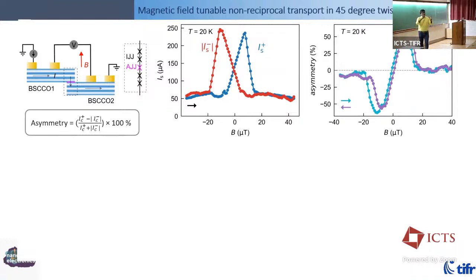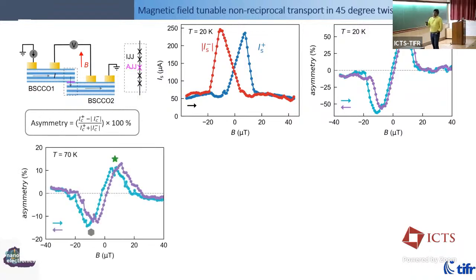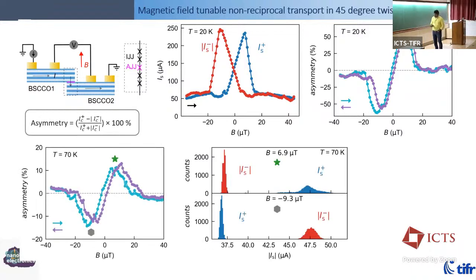So we had to build a special setup, a cryoperm box, to shield out Earth's magnetic field, and then have an electromagnet inside to generate the magnetic field. So this asymmetry can be tuned with a current, and it has some small hysteresis due to magnetic field, and it goes up to about 70 Kelvin.